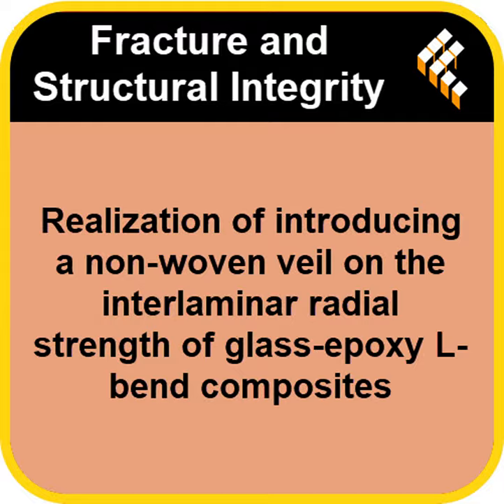Okay, so it's a known issue. People must have tried fixing this before these veils, right? Oh, absolutely. Engineers have been creative. For instance, there's something called the tufting technique. Tufting? Like on a cushion? Sort of. It involves actually stitching threads right through the composite thickness. And that did help. Studies showed it could boost ILRS by around 40%. Okay, interesting. What else? Another approach used tiny metal pins, specifically stainless steel Z-pins, that basically drive these pins through the layers. Like tiny nails holding the layers together. Pretty much. And that was quite effective, too, boosting the curved beam strength, the CBS, by up to maybe 42%.